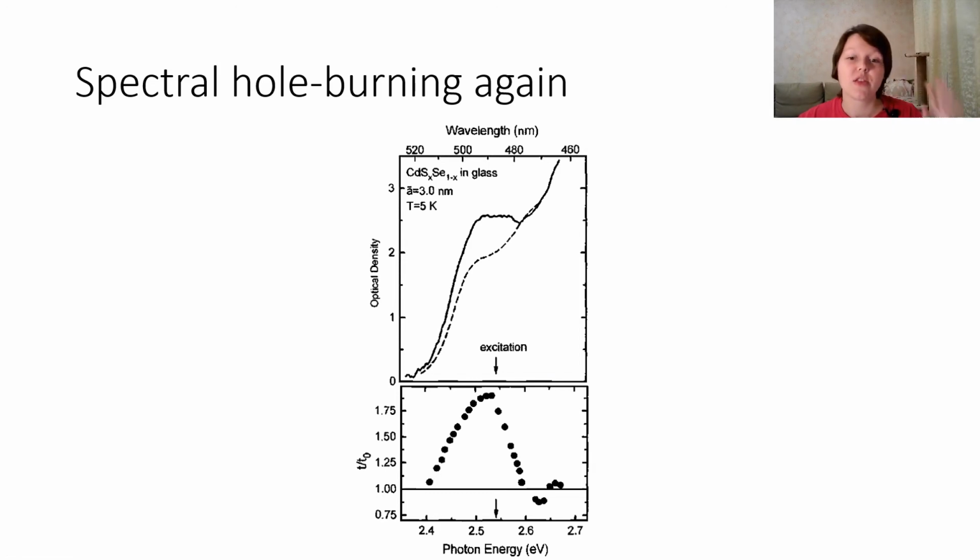But sometimes the shape of the burnt hole spectra is not Lorentzian. Maybe it is Gaussian or even wider, like here. And scientists have found out that the large values of broadening are typical for crystals that were formed during the process of the competitive growth. But in case of the very narrow homogeneous width of the burnt hole inside of the spectra, we are dealing with the crystals that have grown during nucleation stage and normal growth stage.